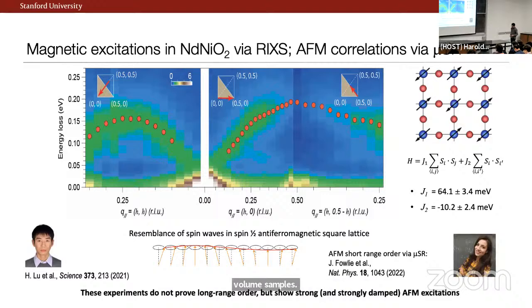And luckily, well, it's good to have friends. So I have friends that are really very good at resonant inelastic X-ray scattering. It's a technique that's really developed significantly over the last 2 decades, where you come in with an X-ray, typically at a synchrotron or a facility like that. A Raman-like process where you can probe things like magnetic excitations, right? And so this is very important for us to be able to probe what happens in these small volume samples. So what did we find?